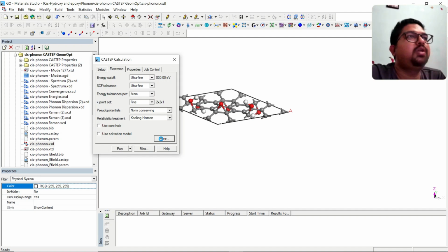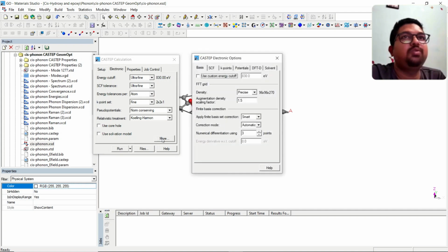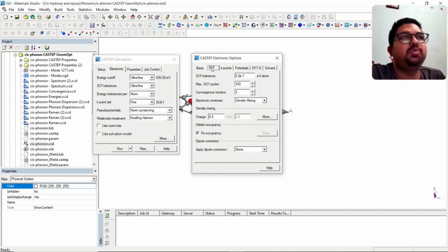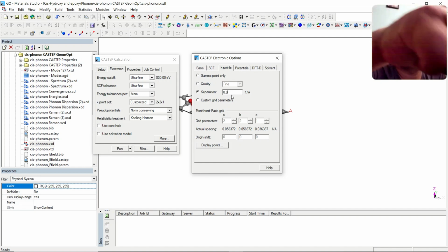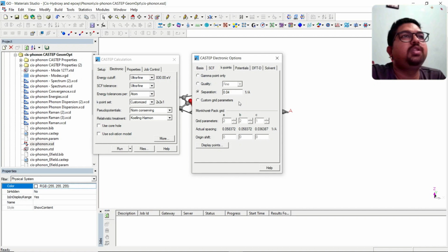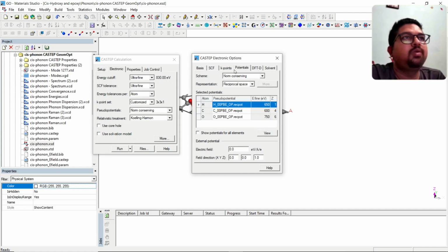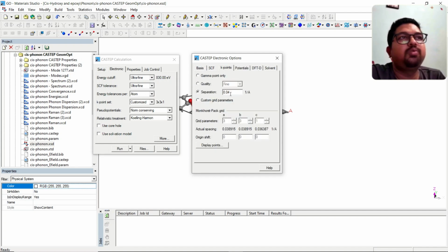If you see over here, actually based on your system, if your system is very strong, or if you're using HPC, then you can have better K points. You can choose 0.04, which will be around, if you see, 3 by 3 by 1 lattice. Okay, so it's up to you. If you give the 0.04 per angstrom separation, it will give you better results. It's up to you.